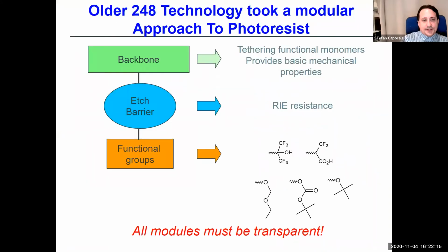So in the older technology for 248, which is where I started my polymer days, we used a very modular approach to designing the materials. We had a backbone that is basically the reactive site to tether all the materials. We put an etch barrier, which resists the etch step, in the middle, and then we functionalized off that group here. And the functionalization we were looking for mainly was something that was base soluble, because they're using a base developer. So some sort of carboxylic acid or pKa hydroxy that's like phenol, about 9, that we could protect. And that way, when the acid hit it, these would deprotect.